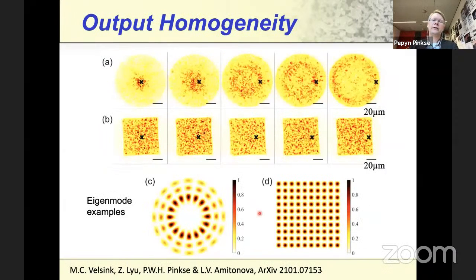Why this is the case is easily seen if you look at the output speckle patterns when you inject a point source at the input, indicated by the black cross, and then move that black cross from the center of the fiber towards the edges. And you see that the light at the output of this round fiber is more or less concentrated at the same radius as where you inject it. So if you move your injection spot to the edge, then also the light comes out at a radius closer to the edge of the fiber. It's quite different from a square core fiber, where we see that the output distribution is much more homogeneously distributed over the area of the fiber. And this is explained by the structure of the eigenmodes, which have this ring-like structure in round core fibers, and they're much more homogeneous for square core fibers.